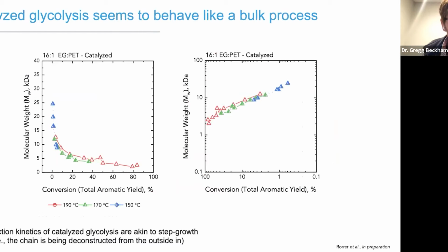And if you look at this in a different way, so now plotting MW as a function of conversion, measured by total aromatic monomer yield, as a function of temperature, all of these collapse onto a single curve essentially. And if you do the same thing with molecular weight, log10 of molecular weight as a function of log10 of conversion as well, starting up here at low conversion and going to high conversion, again, from a polymer physics perspective, you get a collapse of MW onto a single line. And so what this really looks like, if you know polymer synthesis, is step growth kinetics, except of course going in the opposite direction in this case.